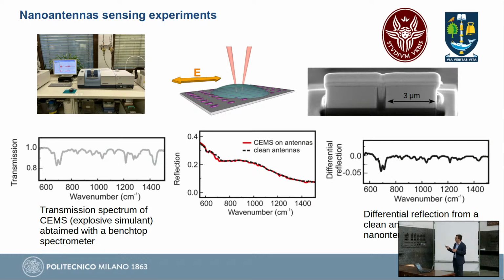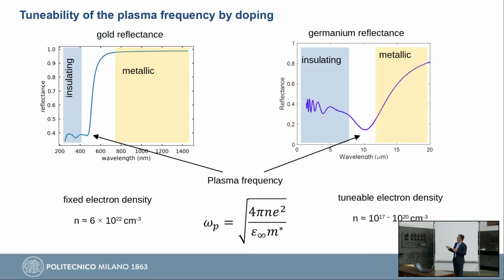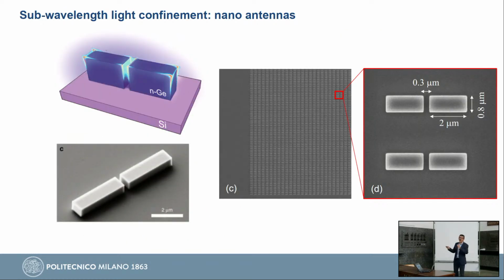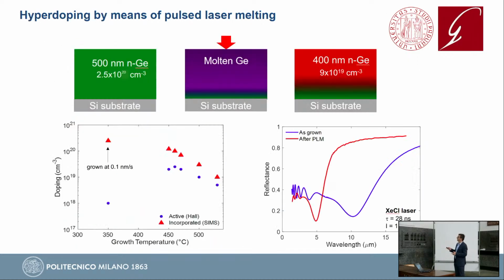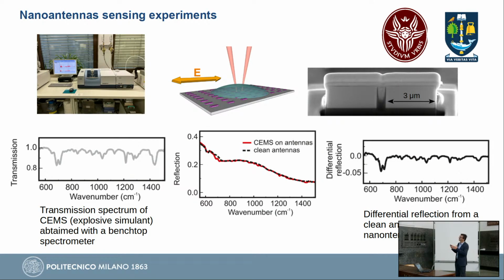It's less effective at longer, higher wave numbers because this resonance we have in this kind of structure is also quite sharp from the point of view of spectral density. So if you want to detect at another wavelength, you need to slightly change the geometry of your system. But this proves essentially that, using silicon and germanium, you can use the possibilities offered by semiconductor technology, formation of heterojunctions, nanofabrication, and doping to actually tailor your material system for a specific application.